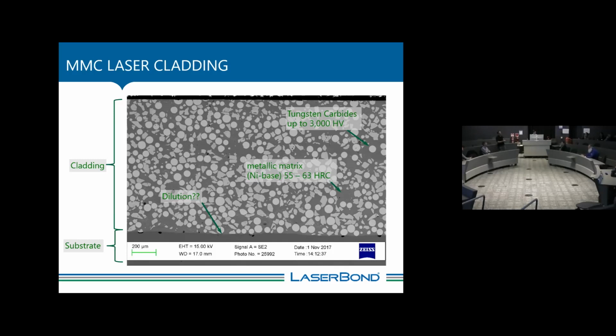So what is in place in the actual cladding is a metallic binder, and the brighter points, that's the carbides, really only distributed here in the cladding. So with just the binder and carbides, we have a lot more to play around with. We can use different binders, harder, softer, more corrosion resistant, less corrosion resistant. Then we even can play around with the carbides, carbide size, carbide types. So the advantage is I can tailor the matrix maybe to combat impact, or I can tailor it towards corrosion resistance.